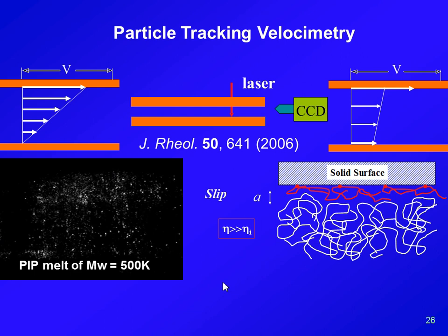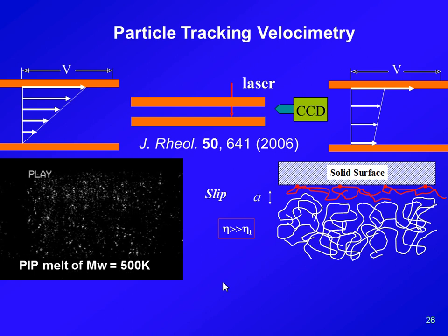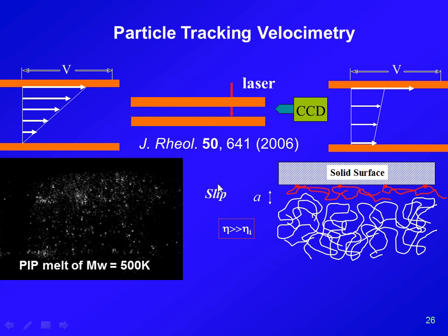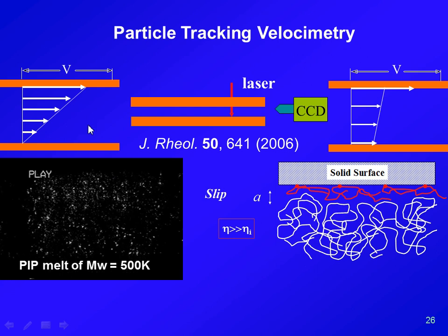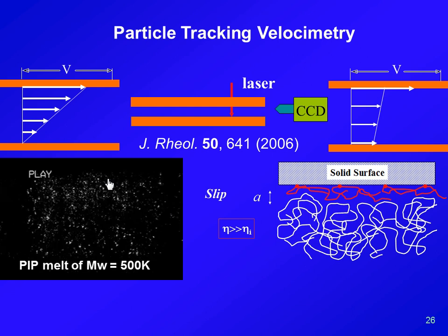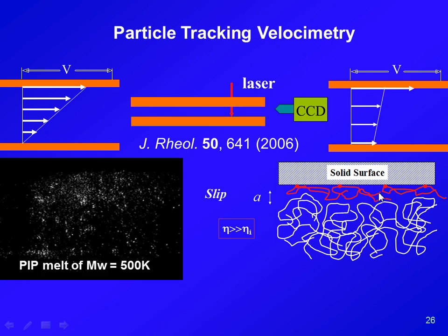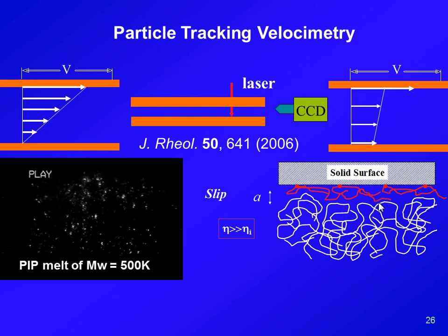And that's the point where the polymer is still in good interaction with the surface. So that allows this shear to continue homogeneously. And the movie subsequently shows, upon breaking, watch, it retracts because there's nothing to grab the sample anymore from the surface. Ultimately, you see, that's ultimately steady state. You have this constant slip, as I depicted. This picture, I had it 15 years ago.